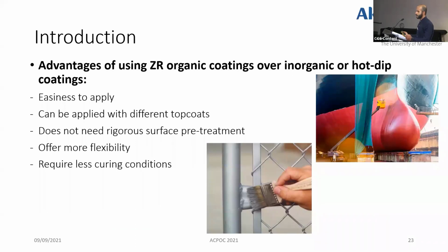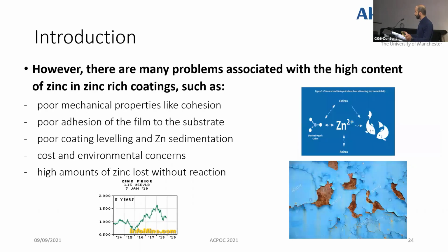There are many advantages of zinc-rich organic coatings over other coatings like inorganic or hot-dip coatings, such as easiness to apply, can be applied with different top coats, does not need any rigorous surface pre-treatment, offers more flexibility, and requires less curing conditions. However, there are still some problems associated with the high amounts of zinc in zinc-rich organic coatings, such as poor mechanical properties like cohesion, poor adhesion of the film to the substrate, poor coating leveling and zinc sedimentation, cost and environmental concerns, and most importantly, high amounts of zinc are lost without any reaction because they are disconnected from each other by the corrosion product of zinc.